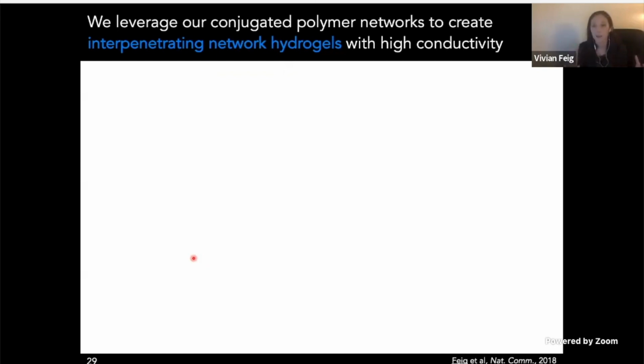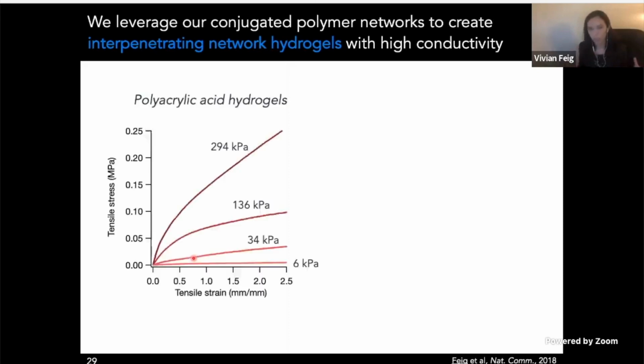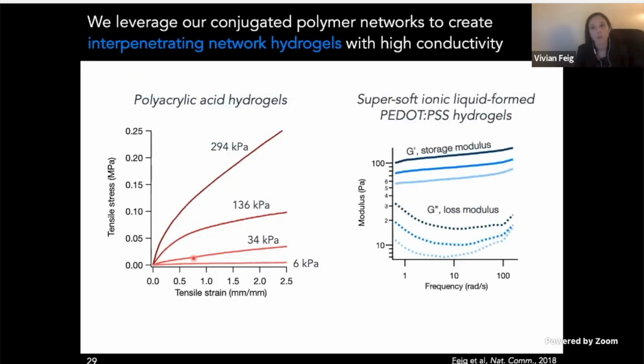a stretchable hydrogel. And so as a proof of concept, we decided to make polyacrylic acid gels, which can be easily stretched to over 250% strain, and that have elastic modulus values within this kilopascal range of interest that we want for biointerfacing. For the conductive network, because we don't want to increase the overall modulus too much beyond these values, and because we want to be able to mold freestanding films for mechanical characterization, we decided to make PEDOT:PSS networks using the ionic liquids that I talked about before.